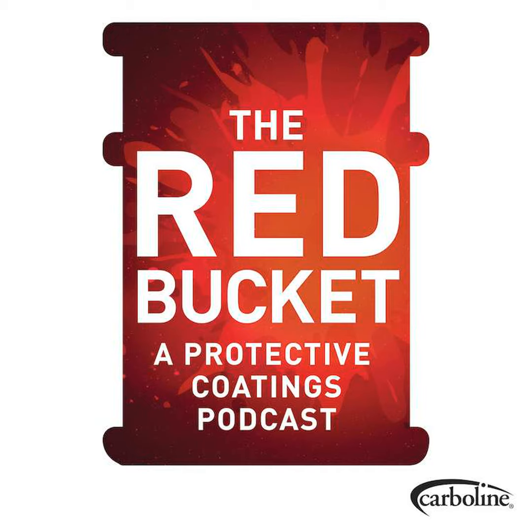And so what we hope to, by doing proper surface prep, just like we do with epoxy coatings on steel, we do the same thing with concrete, is that if there are thermal stresses, they're passed through the film rather than at the bond interface. Right. And that's the most crucial thing, the bond interface. And we know that the concrete's going to be weaker than coatings. That's just a known fact. You can look at physical properties. So with that in mind, if the contractor can do the best that he can under the circumstances he's placed in, then chances are you may have long-term success.